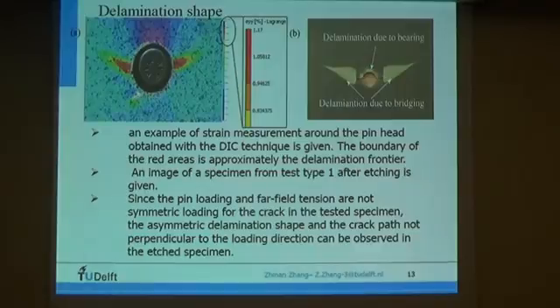Since the pin loading and the far field tension are not symmetric for the crack in the test specimen, the non-symmetric delamination shape and the crack path not perpendicular to the loading direction can be observed. We can say the delamination shape is not symmetric. It is like an angle, up direction, on both sides of the hole.